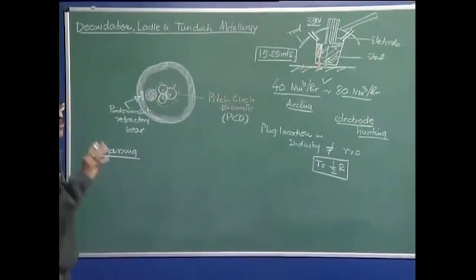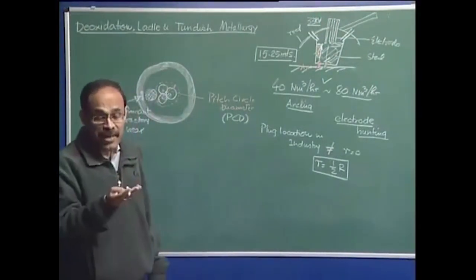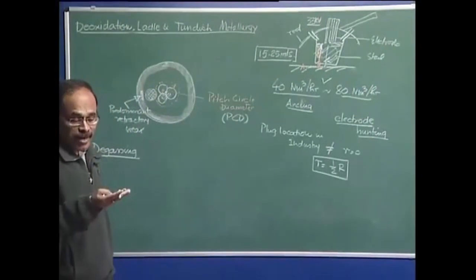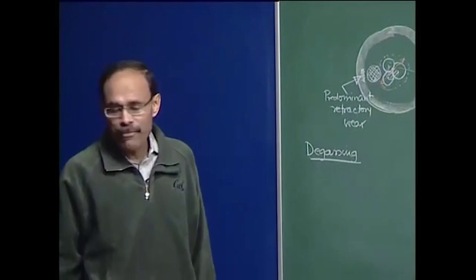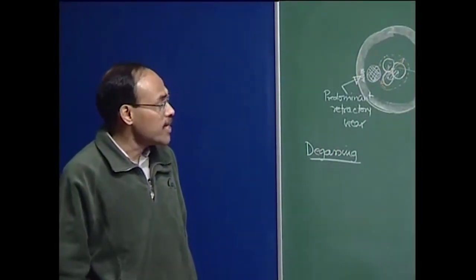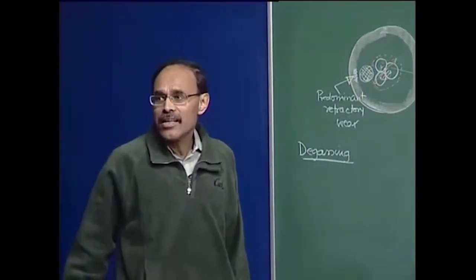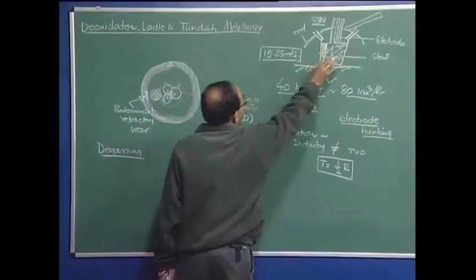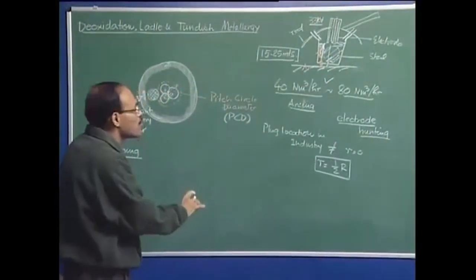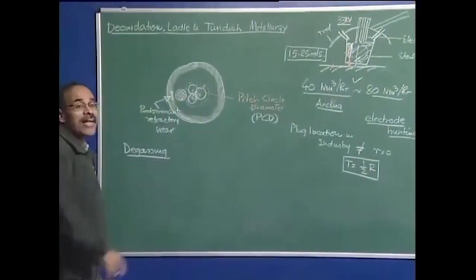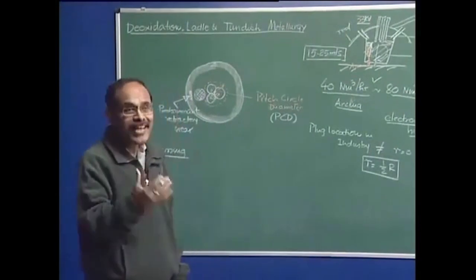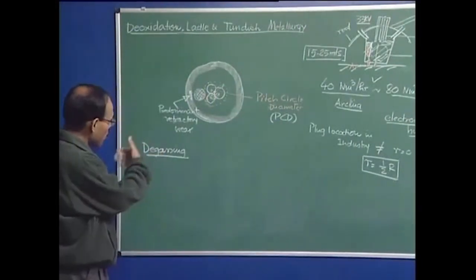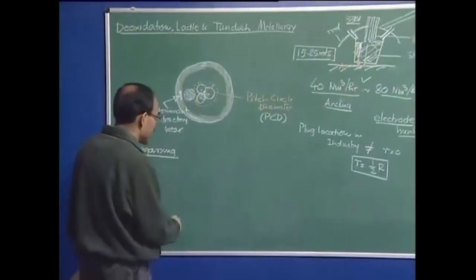If you want very sophisticated grades — Arctic pipeline steel, rail steel — which have very little tolerance for nitrogen and hydrogen (hydrogen causes brittleness, nitrogen impairs toughness drastically; for deep drawing steel, significant nitrogen is not tolerated), then even beyond ladle furnace treatment we may need to eliminate residual nitrogen and hydrogen. The techniques used are the commonly called degassing techniques — specifically vacuum degassing. Degassing is facilitated under vacuum.